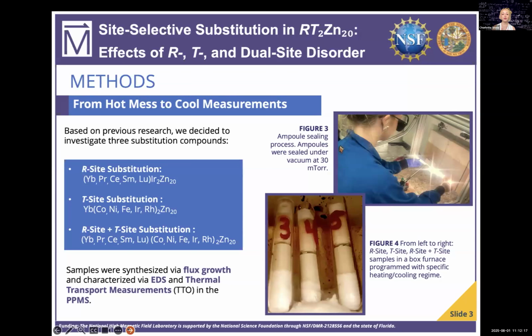I synthesized three new compounds using zinc flux growth, a method where the elements are dissolved in molten zinc and then slowly cooled to form high quality crystals. I made one rare earth compound using ytterbium, praseodymium, cerium, samarium, and lutetium, one transition metal compound using cobalt, nickel, iron, iridium, and rhodium, and one 11-element crystal that combined both rare earth and transition metal disorder at the same time.